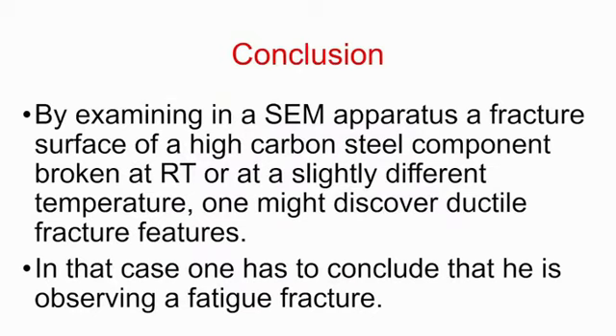So what's your conclusion? If you take a high carbon steel component that has been broken at room temperature or at a slightly different temperature, and if you discover that there are some ductile fracture features, you have to conclude that it was a fatigue fracture, which makes things very simple. You work at not so high magnification because sometimes the samples have not been prepared properly. They have been oxidized by the environment, and you look for features. Do you see some ductile features? It has been fatigue. Thank you very much.